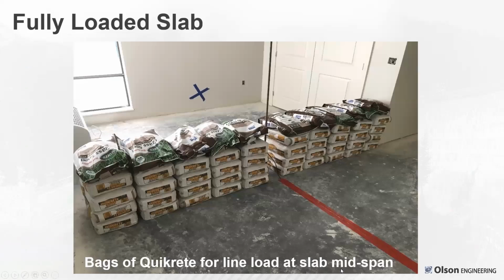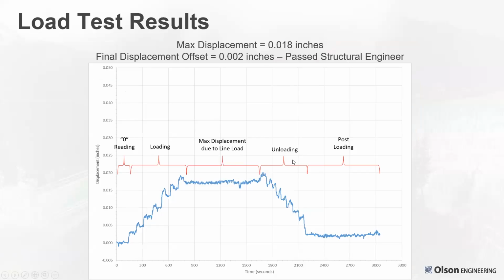So what do we get? Here's the bags of Quikrete for the line load and the lighter bags above it to get it at slab at midspan. You can see where the rod is coming down and we're measuring the displacement in between them. So a simple one. Usually you check several points, but this was truly a simple proof load test. This shows the results as it was being loaded up over that 10-minute period, went up to not very much, 2/100 of an inch, obviously much less than the quarter inch they were worried about. The maximum displacement hit that 2/100 of an inch, then it was unloaded and basically came back almost to where it started at 2/1000 of an inch residual displacement.